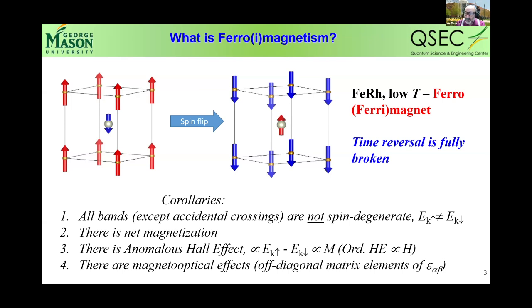There's no reason to have the same energy for two different spins and the same momentum, except maybe accidental crossings. There is, of course, net magnetization. There is anomalous Hall effect. There is also the magneto-optical effect, which is nothing but a finite frequency generalization of the anomalous Hall effect. So all these things are well known. And in fact, interestingly, such things as anomalous Hall effect and the magneto-optical Kerr effect have been routinely used in experiments to determine whether a material is ferromagnetic or not. As we will see, it doesn't always work this way.